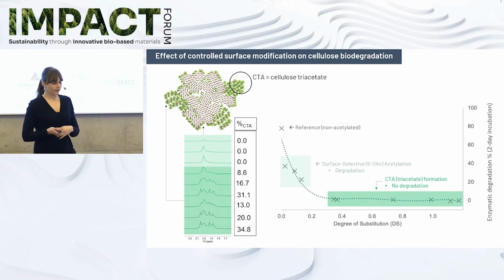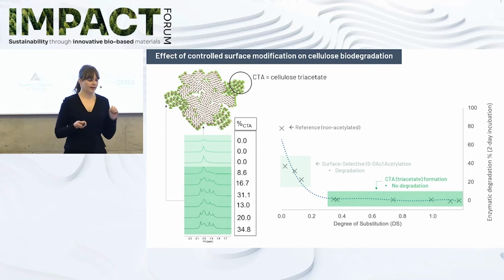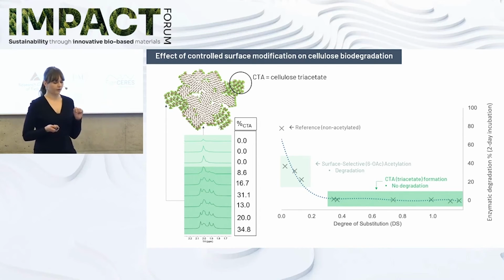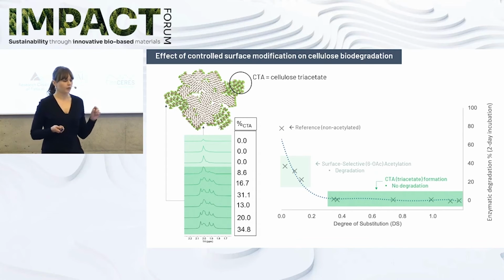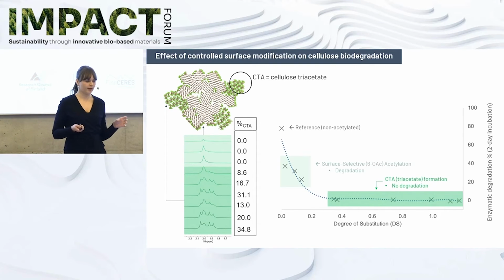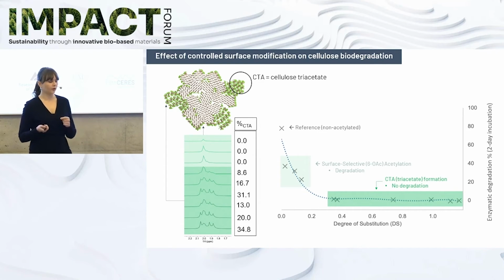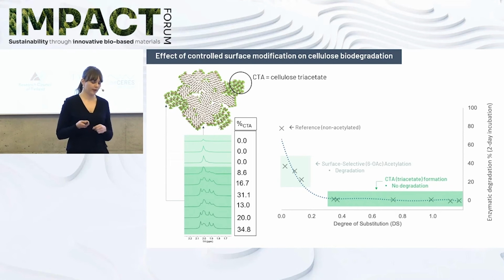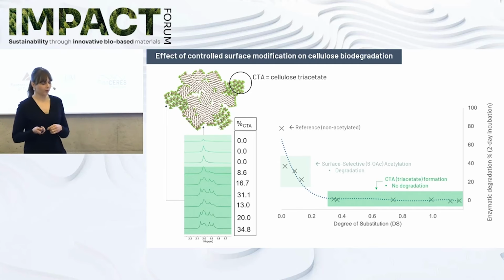And here we can see the similar enzymatic degradation tests, and we see that when we have this very selective acetylation only on the surface chains and there is no cellulose triacetate forming, we still see the degradation in the 2 days. But when we start having these cellulose triacetate domains there, the degradation decreases. And of course, it will depend on if we have longer times. We could see more degradation, and also in different environments, because there are also esterases available to degrade cellulose acetate to some extent, but here we used only these cellulose degrading enzymes.